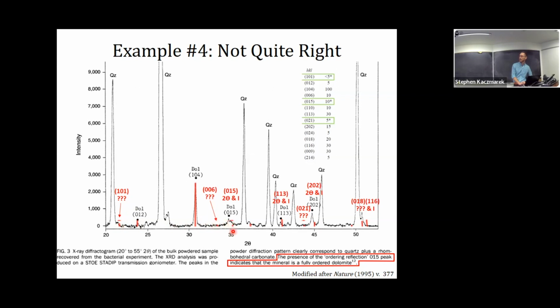Here's our 015. It really should be around 35.3, where that little red dot is by the laser pointer cursor. This is where they marked it, and notice it's got a lot higher intensity than we would expect. So what this would suggest is this is even more ordered than ordered dolomite, which can't really happen.